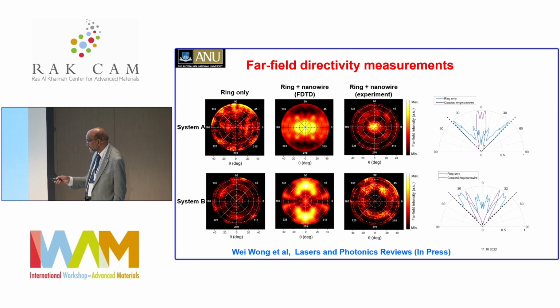Ring only means it's just circulating the light here. The simulations show that once you have the nanowire and ring combination, you expect the light to come out. You can see the experimentally measured ones, the weak coupling and then the strong coupling as well. You can see this coupled device really showing light in the vertical direction. So you can now pack multiple devices so that you can create holograms coming out of our phones, or use it for facial recognition applications, because light is coming out of the plane of the device.